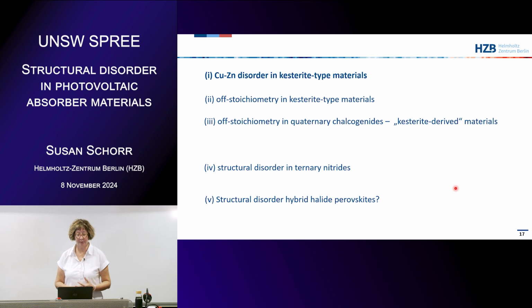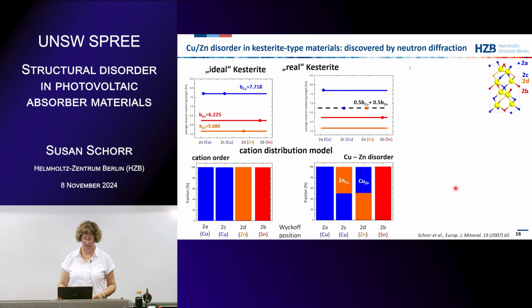As examples, I would like to show you a few points, and I will start with the copper zinc disorder in the kesterite type materials, because we studied this a lot. In principle, the copper zinc disorder was discovered by neutron diffraction. It was the first sample series I synthesized, in 2005 in Leipzig at the university. I did the neutron diffraction and the Rietveld refinement. I made this analysis to compare the experimental and the calculated neutron scattering length.